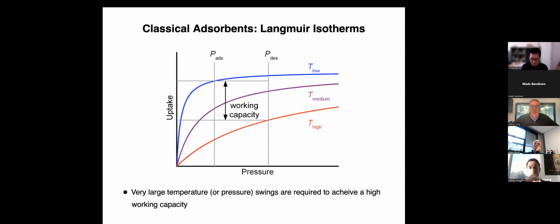And essentially, any adsorbent that you would normally put into such a process, such a column, has a Langmuir type response to the gas molecules. So this is under equilibrium conditions, and this is just a plot of gas uptake versus the pressure of the gas. And for Langmuir adsorption, non-cooperative adsorption, you have this steep rise at low pressures, and then it turns over as you saturate and coat the surface of your adsorbent. And in such a scenario, once you've loaded at your adsorption conditions, the partial pressure of CO2, and whatever temperature you're removing it at, to desorb pure CO2, you either need to go to very deep vacuum or drive to very high temperatures to have any reasonable separation capacity.